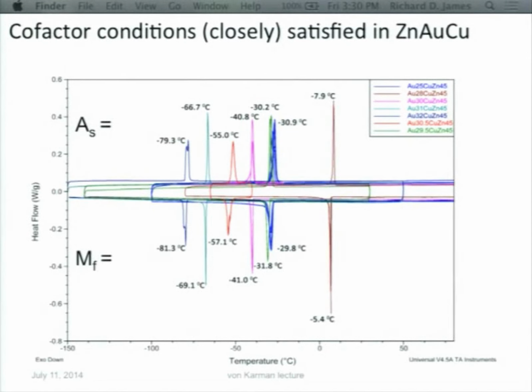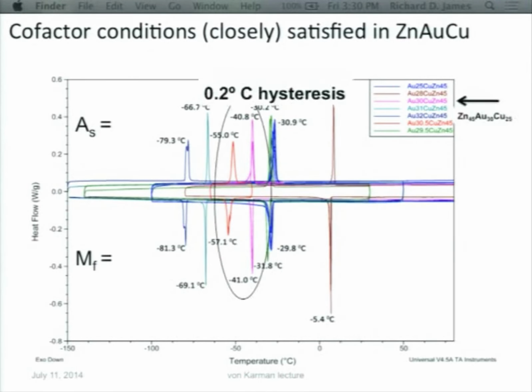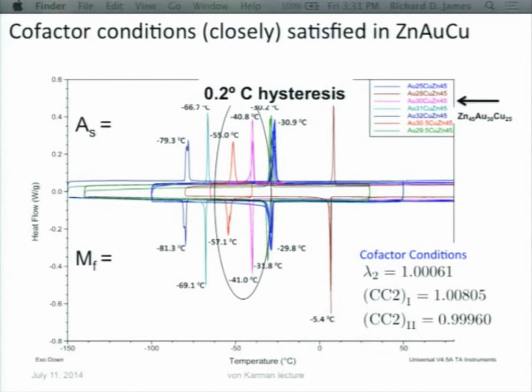So we worked very hard, and again, this is very simplistic. We had an alloy which was nearly satisfying these cofactor conditions. We changed its composition, and we checked whether we got closer to satisfying the conditions or not, and then we systematically marched toward these conditions. We were a bit lucky because our starting alloy was in the zinc, gold, copper system, and we satisfied them for two families of twin systems. That was an accident. Anyway, this is a typical tuned alloy, which is zinc 45, gold 30, copper 25, and in fact it has 0.2 C hysteresis. That's probably a record low hysteresis in a material, which has like 8% transformation strain. It's a big first order phase transformation. So there's a sort of measure of the satisfaction.